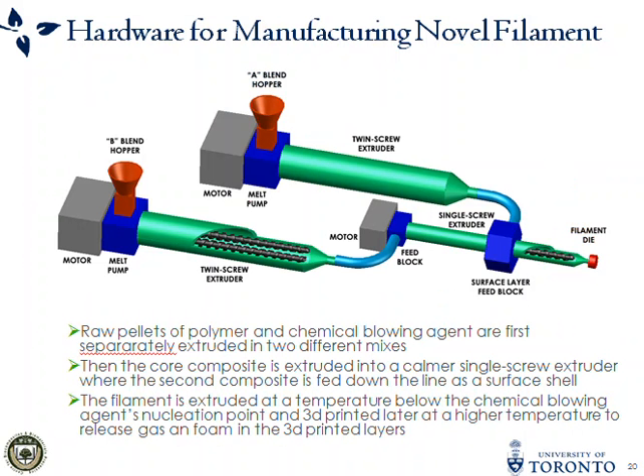So to create this, you would mix your blowing agent with raw pellets in the B blend hopper, and this is going to form the core of the filament. Then you need a second hopper to form the shell with a different blend. So this would be a lower amount of chemical blowing agent, but in my experiments I found it's very difficult to print high performance polymers that are very viscous. So by adding some blowing agent into the shell of the filament, it actually allows it to reduce the temperature required for a good melt flow, and it makes the 3D printing easier. So that's why I would put blowing agent in both sides of the process.